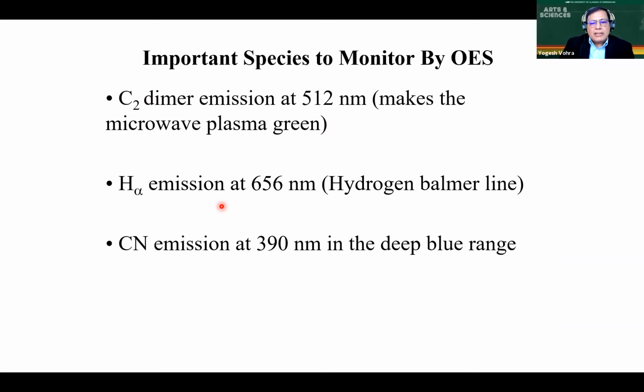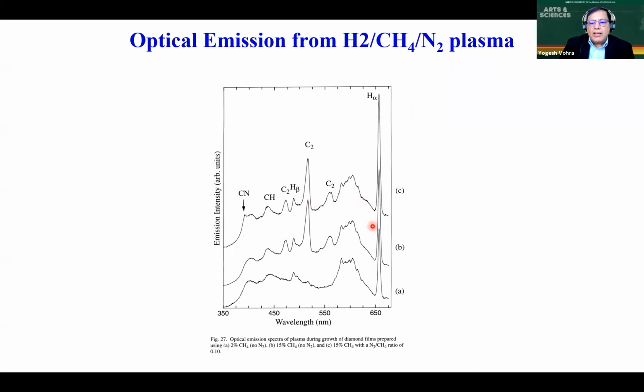Then you have a red emission at 656 nanometers. Those are the hydrogen Balmer lines. And then you have a CN emission, which is in the deep blue range. And that's precisely what we see. This is pure hydrogen plasma. You add methane, you start seeing the carbon dimer. And as you add nitrogen, you begin to see the CN radical in the plasma. So the diagnostics become very useful because you can control the reactive ion species in the plasma.